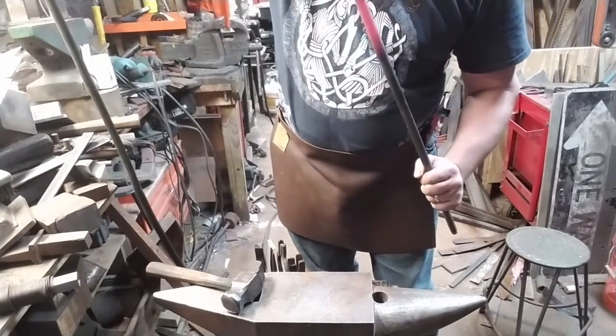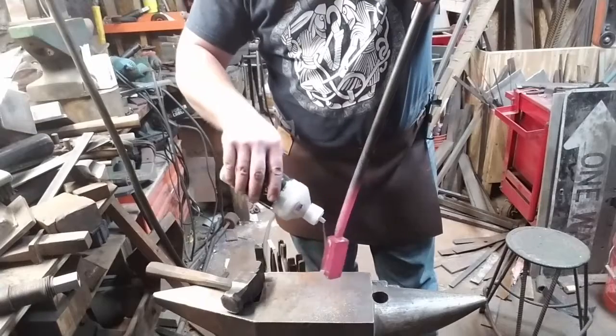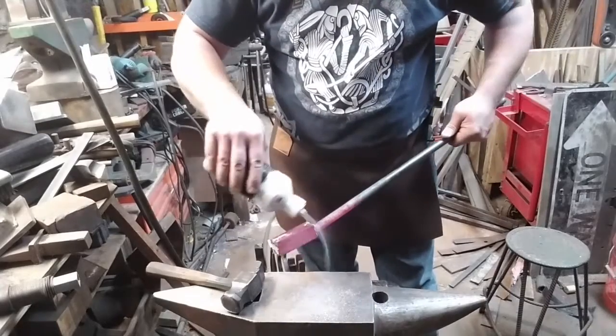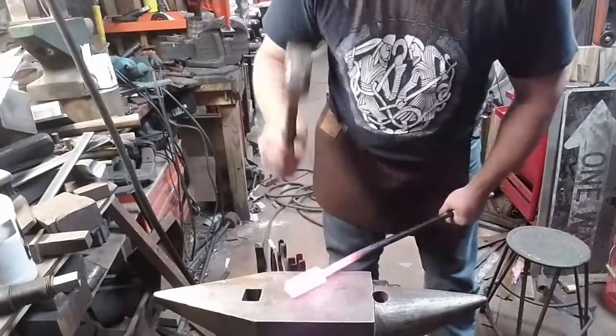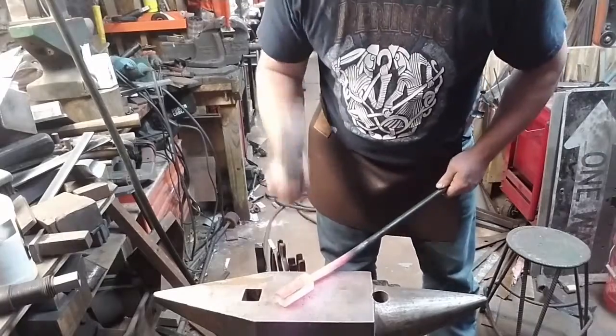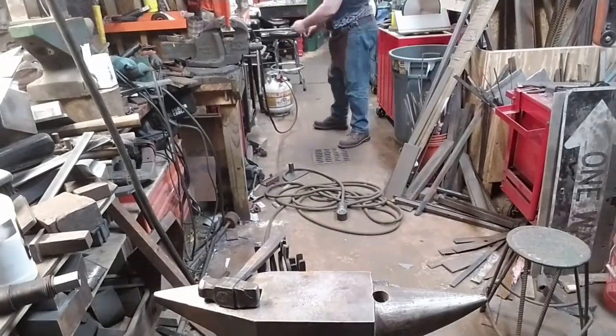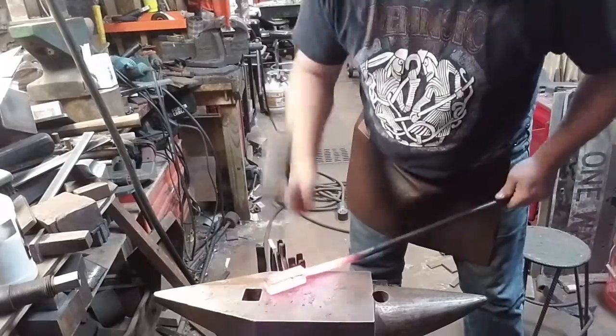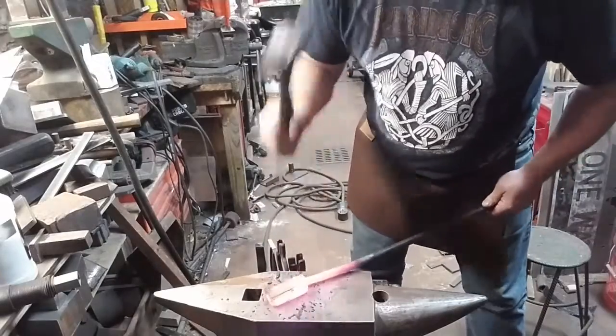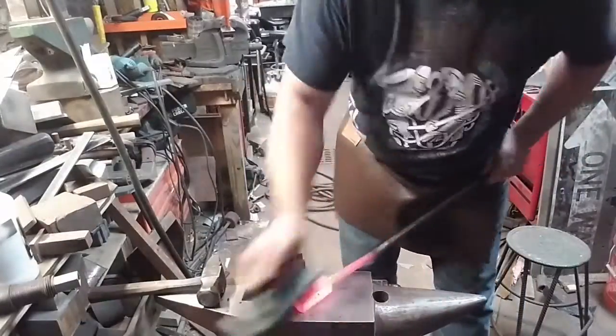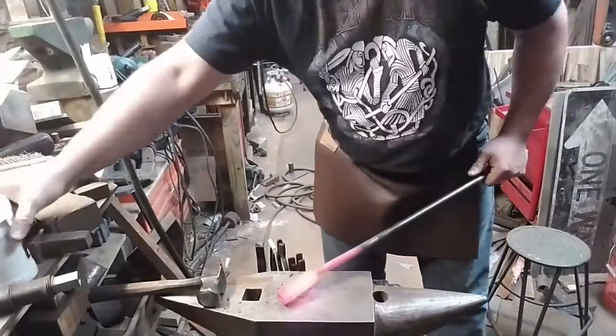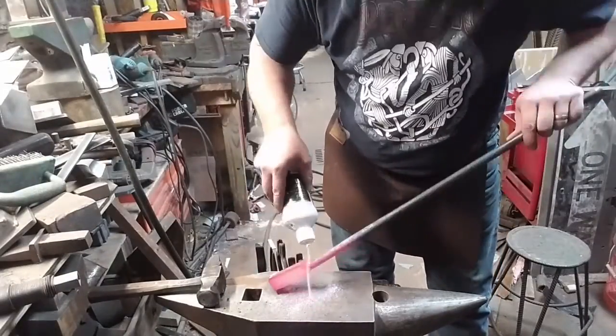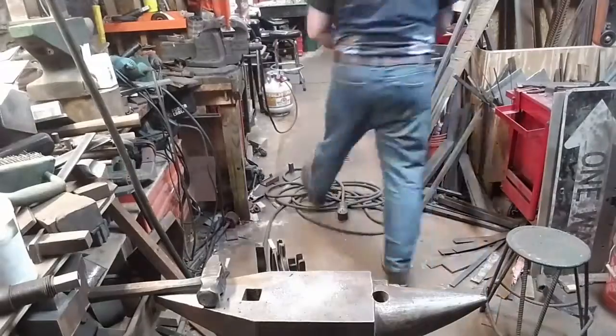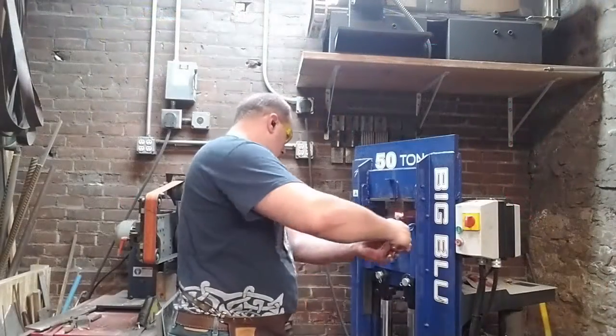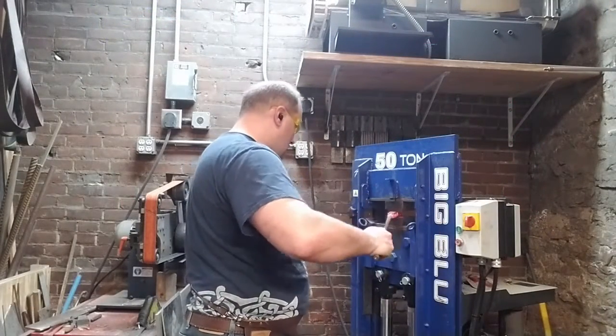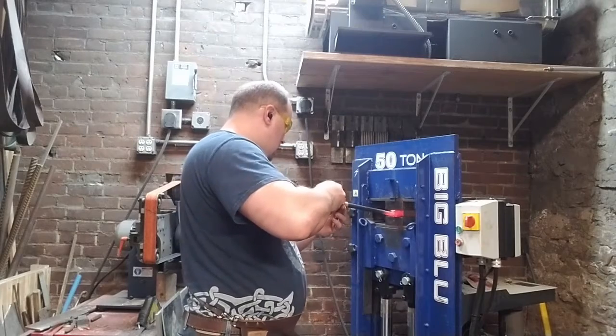Again, I'm using Iron Mountain forging flux. And I can't recommend this stuff enough. Compared to borax, there's no comparison. It's so much cleaner. It allows the welds to set so much easier. It's very difficult to explain how much easier it is to use this flux in comparison to borax, but you really ought to take a chance on it if you're doing any kind of welding in the forge at all.